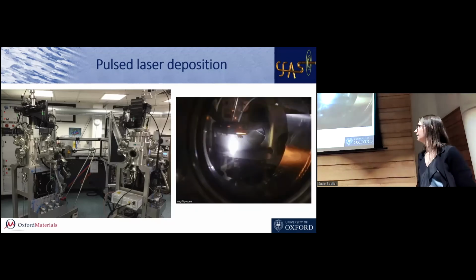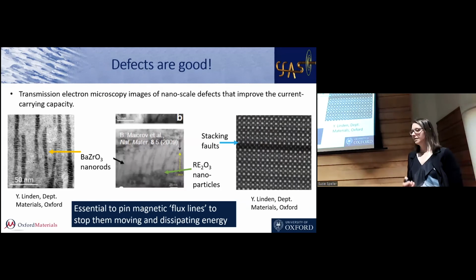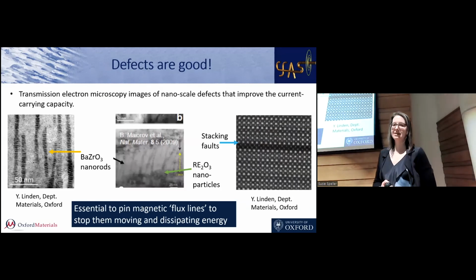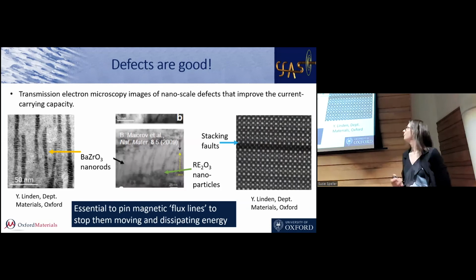It's not the only way of doing it, but it's one way. The last thing I want to say on the coated conductors is that we also have to put defects in them. So they don't work if they're perfect. And for those of you who know something about superconductors, you'll know that it's because inside superconductors, they have magnetic field lines, which we call flux lines. And if they move, then they dissipate energy. They create resistance. So we've got to stop them from moving. And that means we put in defects, loads of defects, any kind of defects we like will pretty much work.